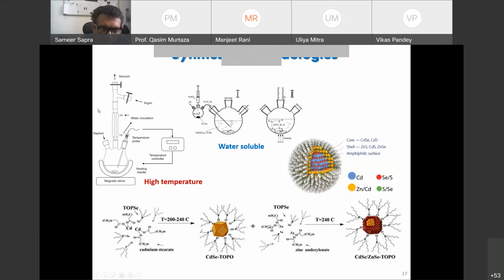Now, this is a solution at room temperature, and here you have 300 degrees. So there's a very vigorous reaction that happens at 300. What happens is cadmium reacts with selenium. It's got a very good affinity, and it immediately forms a lot of nuclei over here at 300 degrees. And then the temperature falls down because you've injected a cold substance into it, to roughly less than 240. And when that happens, at 240 or so, no more nuclei are formed because that vigorous reaction will not happen.